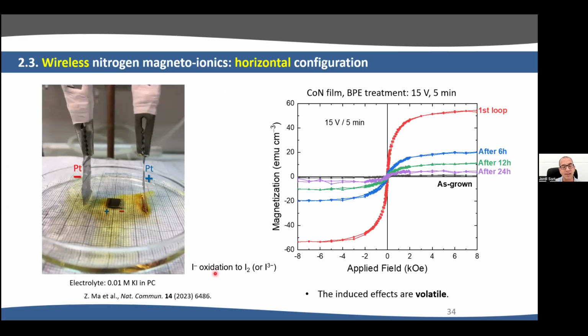I forgot to say that in this case, we introduce potassium iodide in the propylene carbonate, which is our electrolyte, because this increases the strength of the electric double layer. And that's why there is this yellow color, because there is a side reaction at the positive platinum. But what is interesting is that on the right part of the film, we generate cobalt. You can see a shiny appearance, even optically, you can detect that it has been metallized. And we induce a clear ferromagnetic hysteresis loop. The as-grown film was paramagnetic. After applying 15 volts for 5 minutes to these two platinum electrodes, you can generate ferromagnetism.